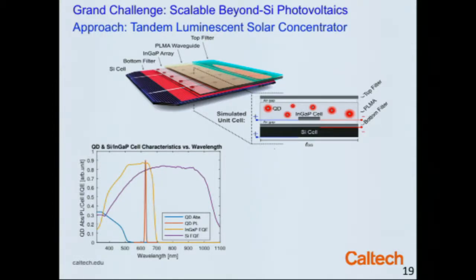That emission is now matched to the band gap of this indium gallium phosphide solar cell, shown in orange. So this photon energy is just above the band edge and is efficiently absorbed in these small solar cells.